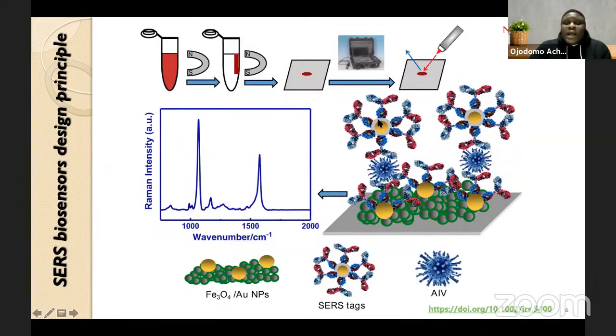So I will show you a very typical example of a Raman principle or Raman SERS application in biosensor design. Basically, what happens in this setup is you prepare your SERS nanotags, and this nanotag contains a plasmonic material, which is the gold in this case, and also you need to coat them around with a reporter. And this reporter is what can give some Raman signal, as shown here, where we can record two distinct peaks. This is actually for MBA that I showed earlier on.